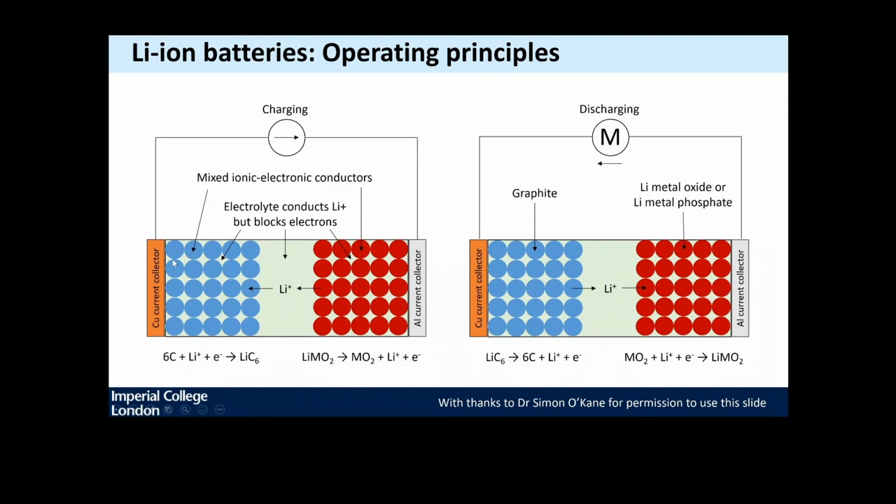One, the fact that I may have a gradient across the electrolyte of species, and so I need to be able to retrieve behavior of electrode that is close to a current collector versus behavior of electrode that is close to the separator. And so this is why you see these rows of blobs rather than just one blob for the electrode like I drew a few slides back. The other effect that we want to be able to retrieve is that the diffusion of Li+ through the solid electrode is the slowest mechanism.